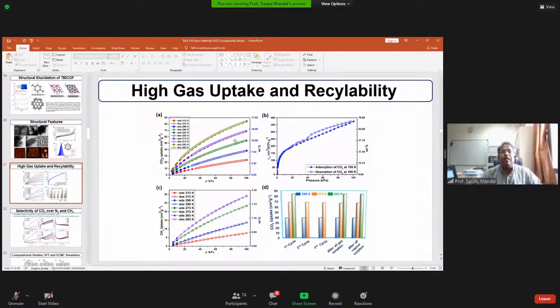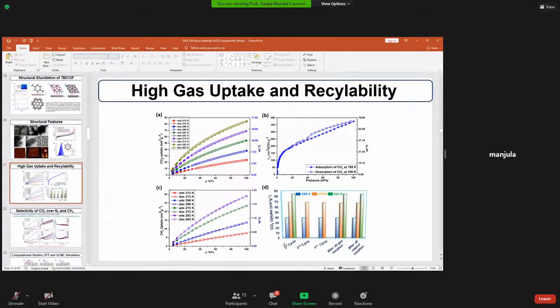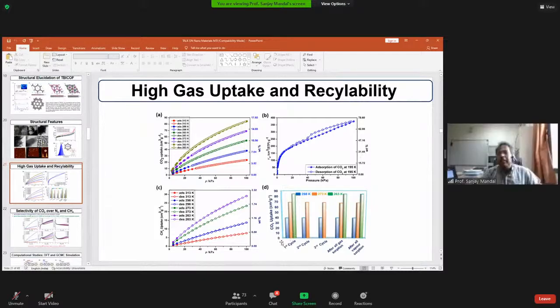and we find out that CO2 is pretty good even at 313 Kelvin. On the other hand, if you do CH4, that goes to about 7 at 313 K. And here we have also looked at 195, which goes to almost 375, okay? And we found that we can really recycle. That means this material after 3 cycles is giving the same, and also after vapor adsorption, it is remaining the same at 3 different temperatures.